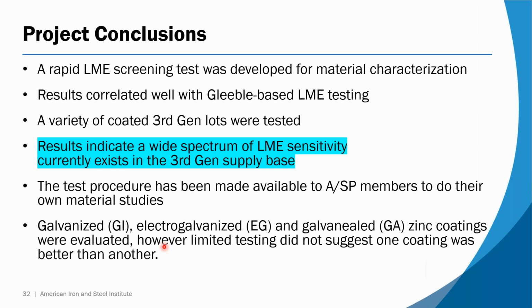So in conclusion, we developed a rapid LME screening test using spot welding. It was taking like a month to test a material using a Gleeble tester. I know some people can do it much quicker, but with students down at OSU and solving problems with our argon purge and things like that, it ended up taking us a month to do a sample. With the spot welding test, it's like a day to weld it and 2 days to do the metallography and write up a report. So we went from 30 days to 3 days. So much quicker and low infrastructure, because now you don't need a Gleeble tester. You can just use a spot welder.